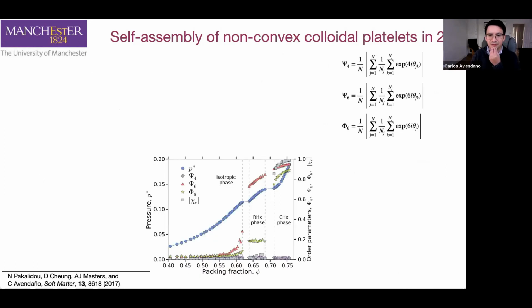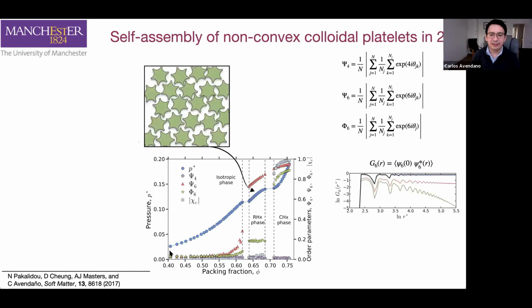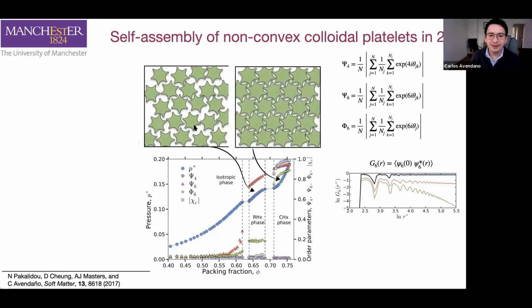First, I will show you the results for the non-convex hexagons, in which in the x-axis, again, I have the packing fraction, in the y-axis, I have the pressure. We start first at low densities where nothing will happen, so we will have just the typical isotropic phase. But then suddenly we observe a phase transition in which the particles start forming a hexagonal phase. But if we pack even more, or we increase the density even more, we start to observe that the particles will start forming that shifting between the edges that I was discussing before.